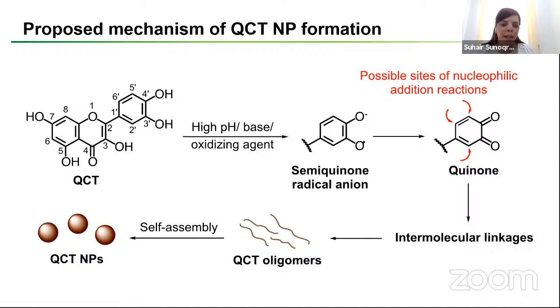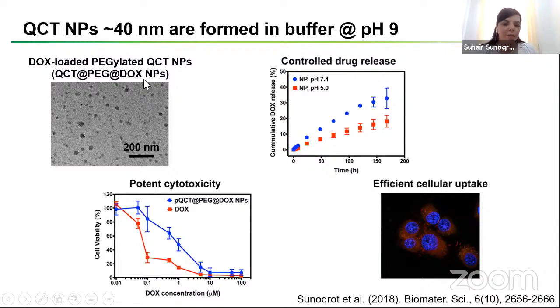So over the last 3 or 4 years, we've been trying to manipulate the reaction conditions, and fortunately, we were able to successfully form nanoparticles of different sizes and different properties. For example, our first attempt was to incubate quercetin in an alkaline buffer at pH 9. And through a series of purifications, we were able to obtain nanoparticles around 40 nanometers in size. We were able to load them with doxorubicin as an anti-cancer drug, and also with polyethylene glycol to make them sterically stable. And we were able to achieve controlled drug release. The nanoparticles were slightly less potent than the free drug, most likely because of the delayed release of the drug.